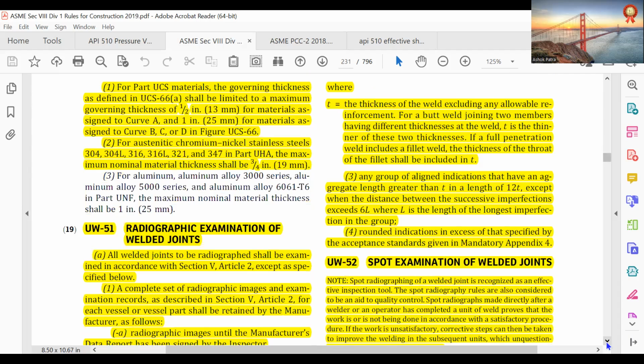For Part UCS material, the governing thickness as defined in UCS-66(a) shall be limited to a maximum governing thickness of 1/2 inch, 13 mm, for material assigned to Curve A, and 1 inch for material assigned to Curve B, C or D in Figure UCS-66. For austenitic chromium-nickel stainless steels 304, 304L, 316, 316L, 321, 347 under Part UHA, the maximum nominal material thickness shall be 3/4 inch, 19 mm.